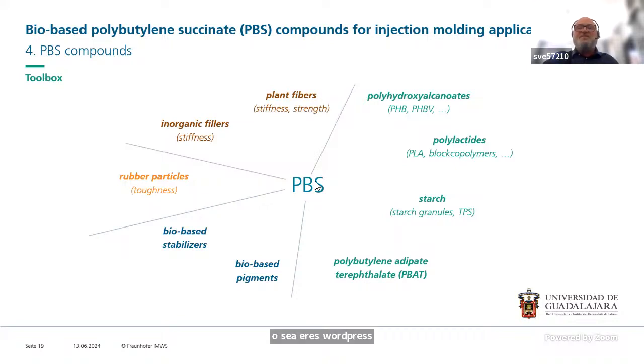We have the PBS as the base material, and now we go on with inorganic fillers to increase the stiffness. We can use plant fibers like cellulose fibers to increase stiffness and strength. We can blend it with other bio-based polymers like the polyhydroxyalkanoates, polylactides. We can use starch as granules or as thermoplastic starch. We can use the PBAT as a blend partner, and we can use bio-based additives like bio-based stabilizers, bio-based pigments. There's also one company, one startup producing such bio-based additives for our polymers.